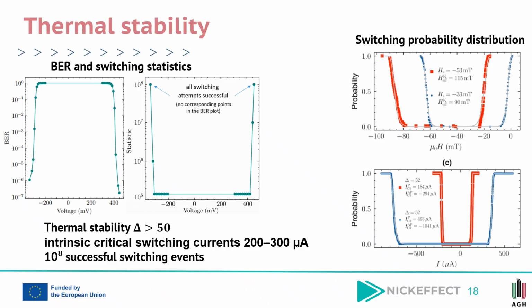From the fitting procedure, the active thermal stability factor delta and the intrinsic critical switching currents were extracted. The optimized devices exhibit thermal stability factors exceeding 50, together with representative intrinsic critical switching currents in the range of approximately 200 to 300 microamps. This demonstrates a favorable balance between thermal stability and switching efficiency, which is essential for practical STT-MRAM applications.